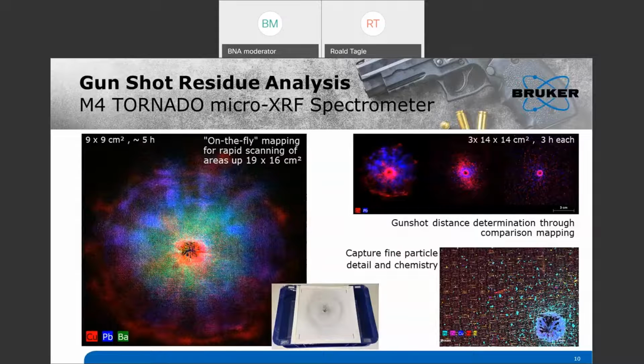But in the area of the gunshot, for example, that we're showing there, we can cover it and get very similar results within an hour or less. But you will not have the high resolution, you will not have the good contrast, but in principle, you will be able to see the enrichment and all of that. It depends a lot, as I was saying before, on the analytical question how long the measurement might take.